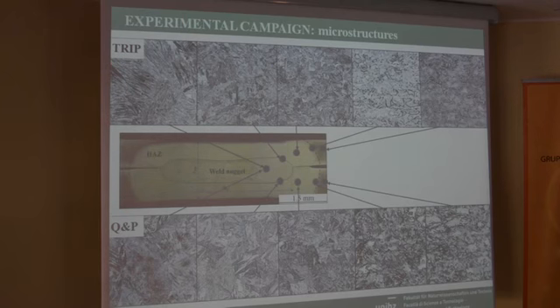Here you can see in more detail the microstructures of the two steels after the welding process. In particular, you can see in this region the weld nugget, that is the region of the steels that melted during the welding process. Then we have around the weld nugget the heat affected zone, and outside this region the base materials.